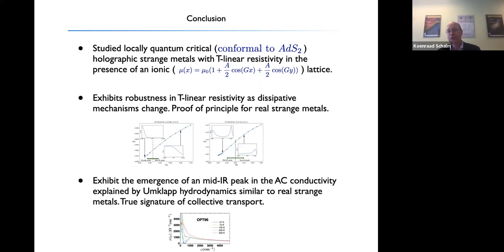So to summarize this story, we've studied the locally quantum critical, the conformal to AdS2 holographic strange metals. They are constructed in this Gubser-Rocha conformal to AdS2 such that, on scaling analysis, you expect them to have a T-linear resistivity. And then we have placed this system in an ionic lattice. And what we then showed, very much to our own surprise, is that this exhibits a very strong robustness in the T-linear resistivity as the dissipative mechanisms in this object change.